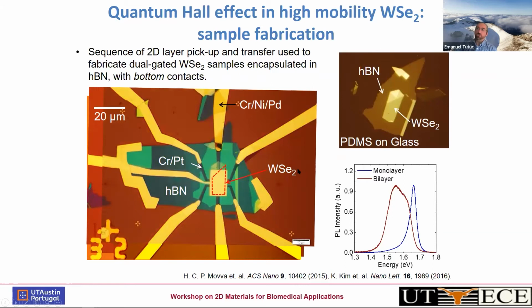And then we do E-beam lithography to pattern a top gate, that is a metal gate in this case. There are devices where we prefer a graphene gate, depending on the requirement of the device. So this is one example of a process flow, and this allows the electrons in a transition metal dichalcogenide to have a higher mobility.